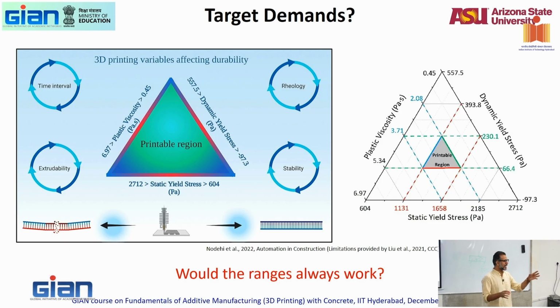I do a trial in a lab in my little desktop printer and I take it to the field. Yes, the yield stress in my lab mix was 80 Pascal. And I go and that 80 Pascal paste, when combined with those aggregates, I tried, and I got a workable mix. You can keep that as a standard reference, but you can never say that that's the yield stress of that paste, that concrete. It's a different value, right? So again, it's complicated. It is confusing. It will be like that because we really can't have one measure that goes into the entire spectrum.